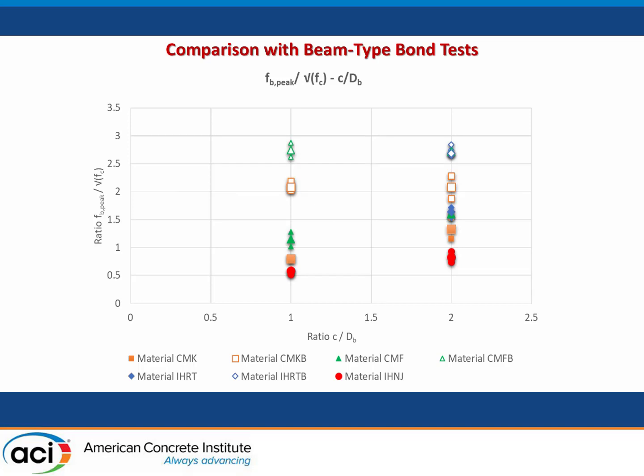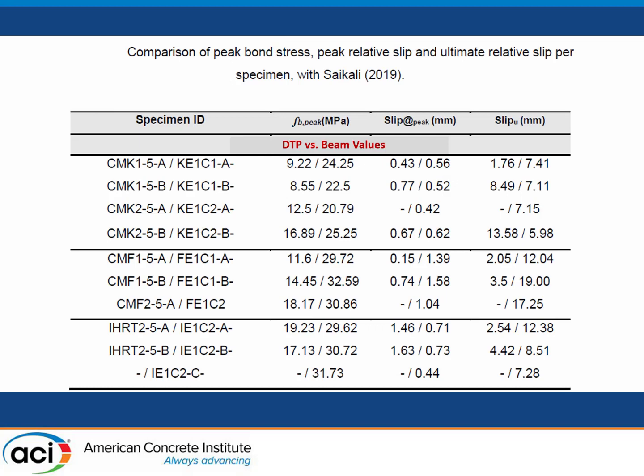And here is the same set of data, but now the bond strength is divided by the square root of the compressive strength of the respective material. We see that with tension pullout, we have a bond capacity in the range of half to maybe 1.3 times the square root of f'c, whereas the beam tests give a much higher value of bond, which in the context of where it is going to be used, is totally unconservative.